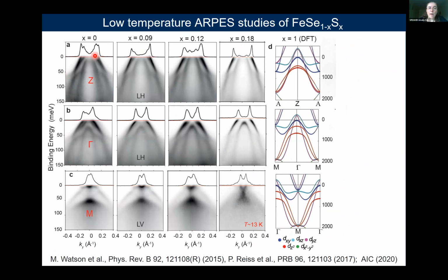And these are the two bands I discussed initially, alpha and beta, and at about 50 milli-electron volts, we have this highly renormalized dxy band, which is present for all the different concentrations. The Z and the gamma point have slightly different dispersions because we have a corrugated cylinder, but the general form in these pictures is pretty similar, and hardly any changes are visible.